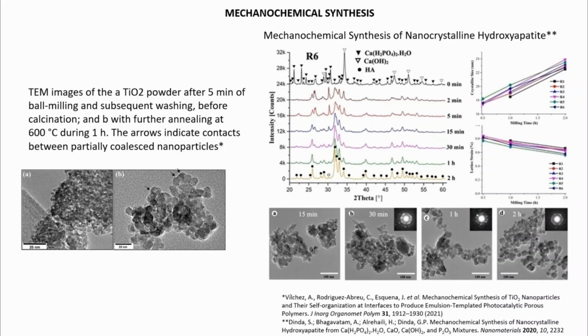As reported, Dinda and colleagues found hydroxyapatite after 2 hours of high-energy ball milling in an ambient atmosphere completely transformed into nanocrystalline powder from initial reagents. The crystalline size of all 6 powder mixtures was found by the authors to be in the range of 18 to 20 nanometers after 1 hour and between 20 to 23 nanometers after 2 hours of milling.